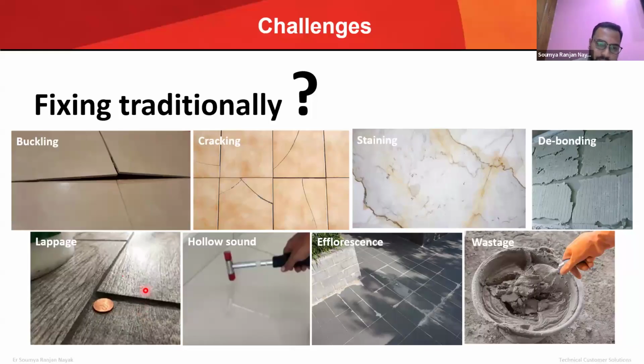If you don't cure it, this kind of lapping issue happens due to improper strength and shrinkage. Hollow sounds happen, and from this point tiles and stones will crack, and due to gaps water enters and efflorescence happens. And obviously we know cement is not a thixotropic material. So when we apply tiles, going forward I will show what type of loads are going to come over a tile, and what behavior the adhesives have to experience. In vertical walls, obviously cement is not a thixotropic material.